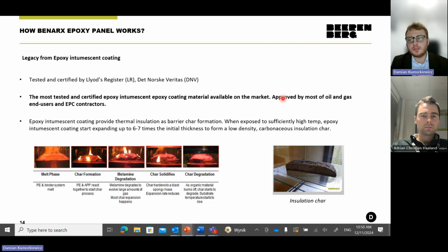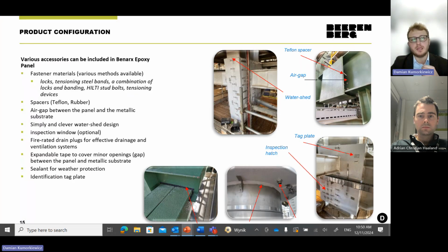How our panel works: basically it works in the same manner as wet applied epoxy intumescent coating on a metallic substrate. When in contact with fire, it will start swelling and expanding up to 6-7 times the original dry thickness, creating this black insulation char around the metallic substrate to protect against hydrocarbon fire.